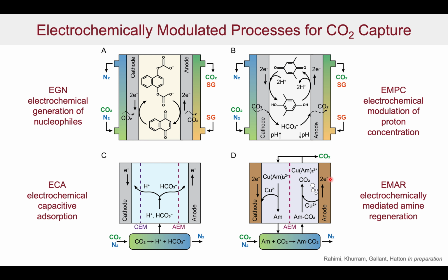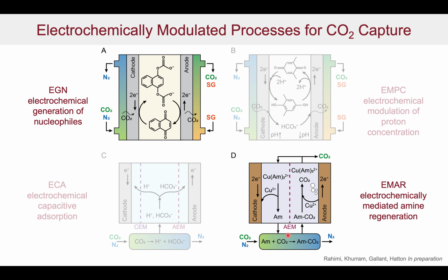A third case of interest is another indirect situation in which we've got an amine plus carbon dioxide forming the amine carbon dioxide product, and we then feed that through to an anode chamber where we release copper ions. These copper ions will then displace the CO2 from the amines, so you get CO2 coming off. And then we can take the copper amine solution and send it back to the cathode chamber, where we reduce it, and the copper comes off, and we regenerate the amine. And we can have this kind of a cycle. I'm going to talk about these two cases in particular right now.